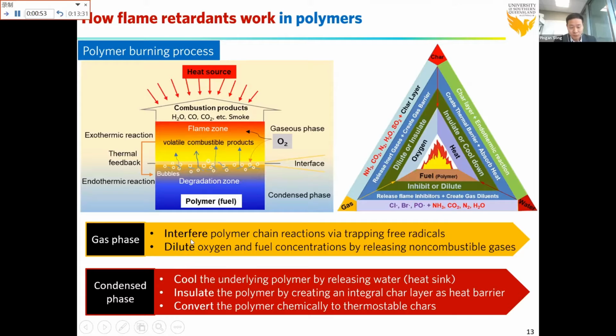In the gas phase, you can interrupt the polymer burning chain reaction by trapping free radicals, or dilute the oxygen or fuel concentration by releasing non-combustible gases. You can also cool the underlying polymer by releasing water or acting as a heat sink. Or you can insulate the polymer by creating a char layer as a heat barrier. Lastly, you can convert the polymer into a thermostable char, because the char is non-combustible.